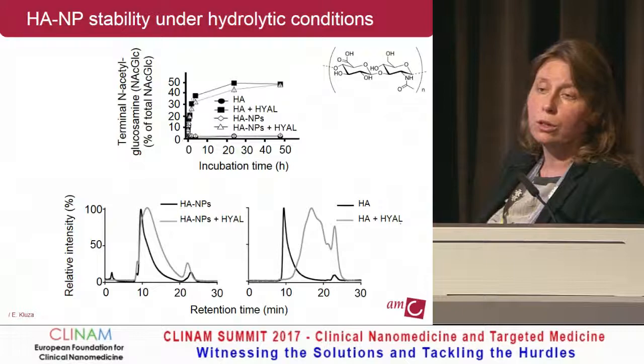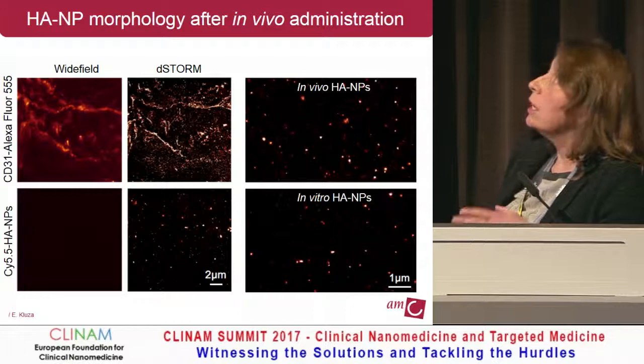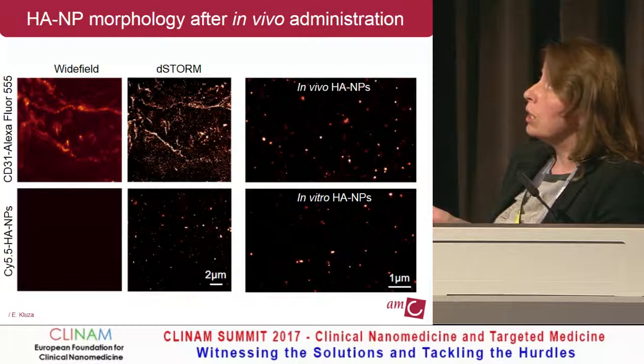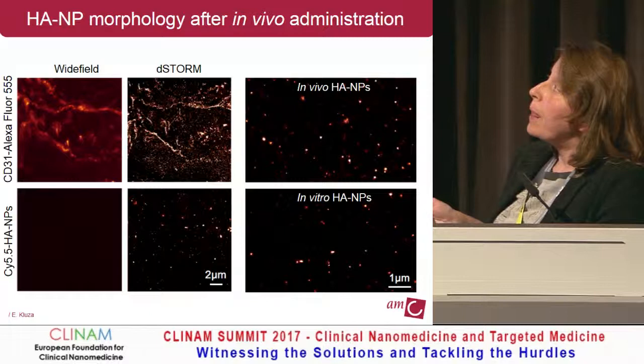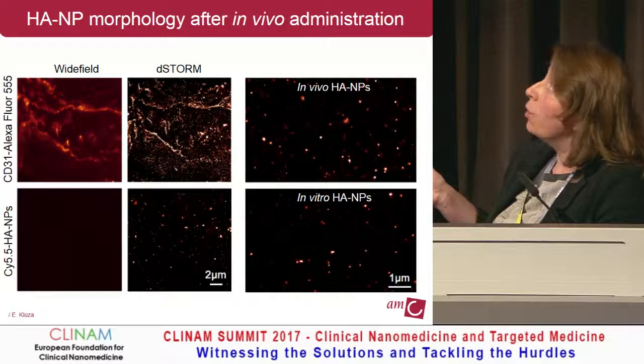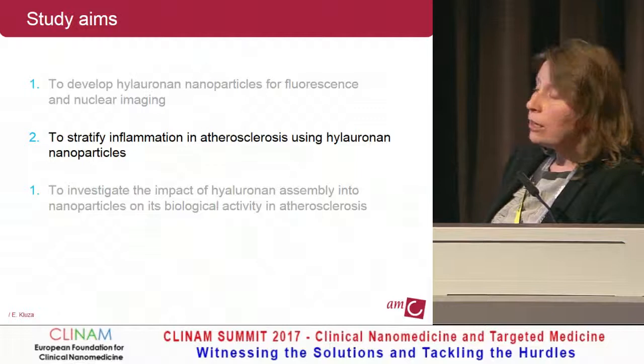We were also very interested in what happens after in vivo administration. We injected the material, harvested the aortas, and visualized with two-color super-resolution fluorescent microscopy the endothelial layer covering the plaques. You can see the CD31-stained endothelial cells and the diffusely distributed nanoparticles. Comparing the ex vivo image to nanoparticles seeded in vitro on cover glass, the morphology is hardly changed. Our main point was whether we can use these nanoparticles to stratify inflammation in atherosclerosis.